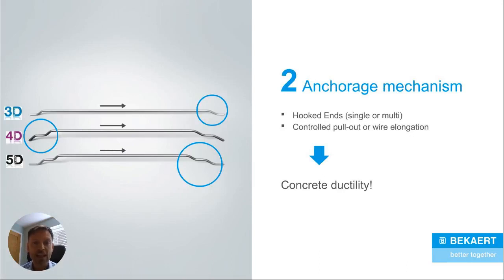The second important factor is the anchorage mechanism. So this is effectively the shape of the fibre. If you could see these three fibres on the screen, Dramix 3D, 4D and 5D, they all have different shapes. The idea is that these shapes are called anchors and they lock into the concrete to provide concrete ductility.